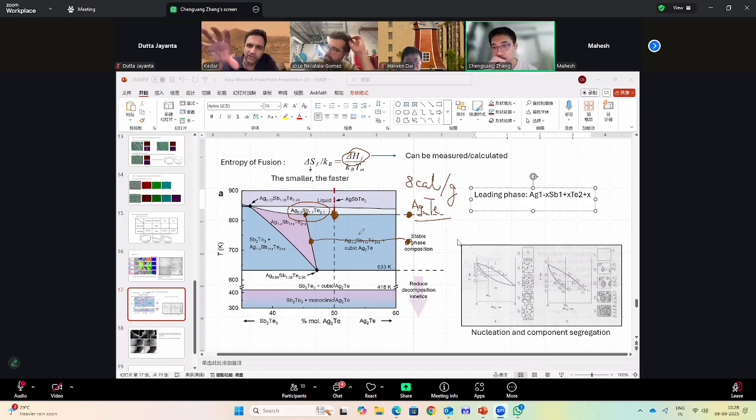The atoms are in their fixed positions, right? So the formation of those bonds for the perfectly crystalline structure should be well captured by a calculation of formation energy. Then what will change is the configurational entropy, which typically for a ternary compound is not so bad. It's an order of magnitude lower. There are some papers that show this.